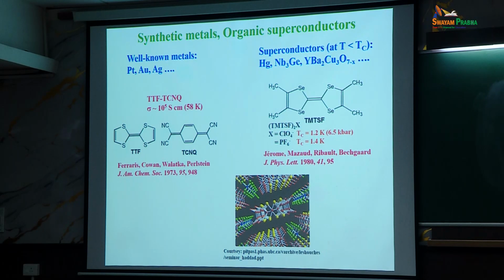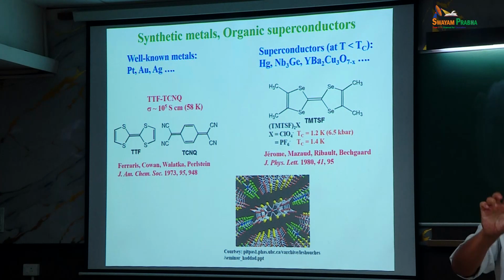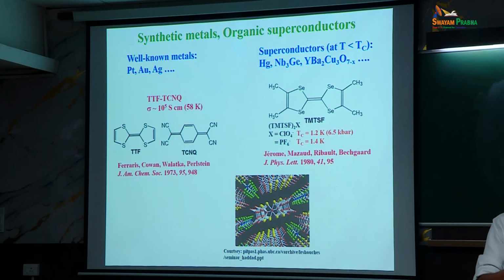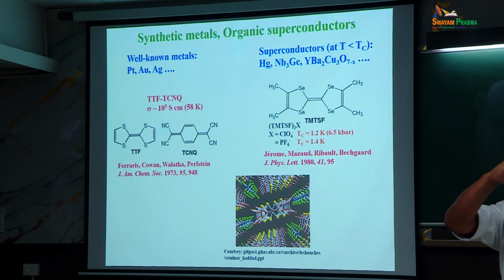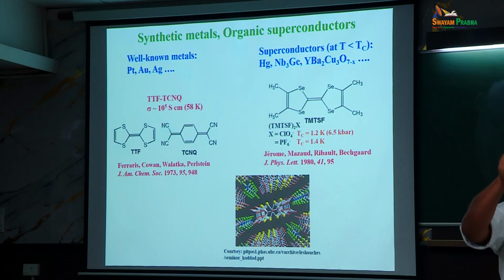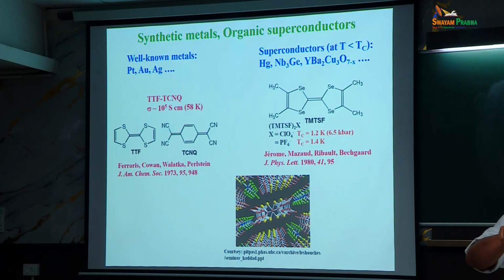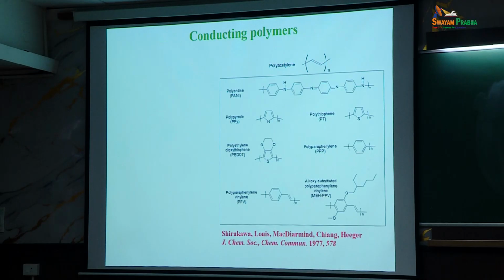Now, very interestingly, they have crystal structures, right? These are crystalline materials. So if you measure conductivity, if you make a crystal, let's say this is a crystal of this compound, the molecules are stacked in this direction. If you measure conductivity in this direction, it will be very high. If you measure in this direction, it will be very low. So these are called anisotropic conductors. So these are all things which are very unique. In gold, for example, you will have very little anisotropy because they have certain cubic structures. So in any direction, they will have similar conductivity. So it depends on the material structure.